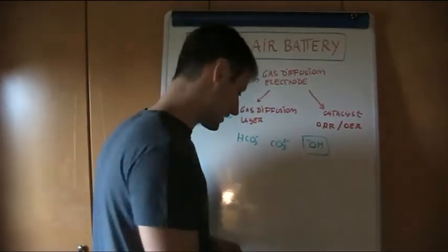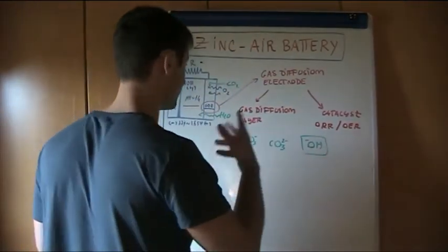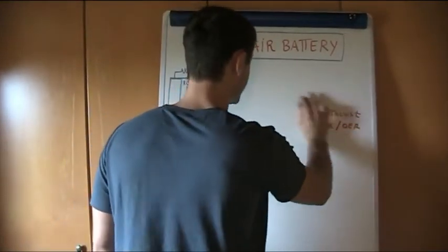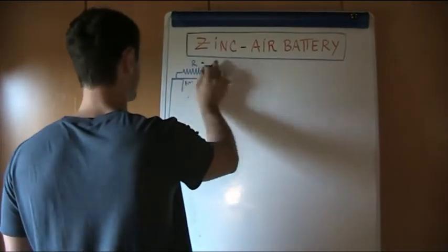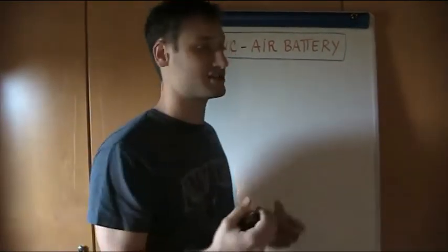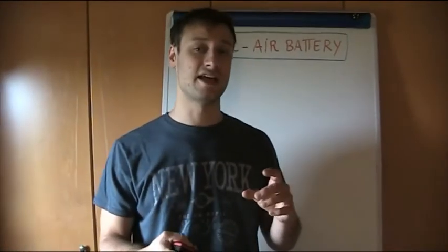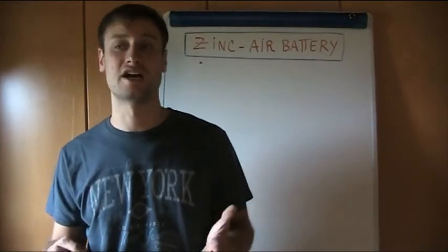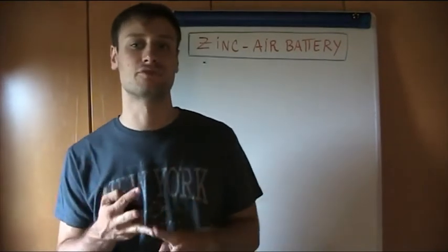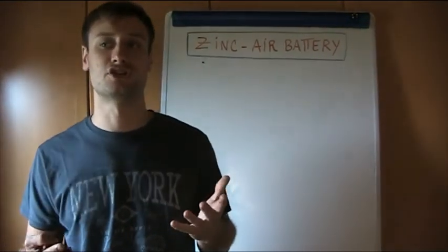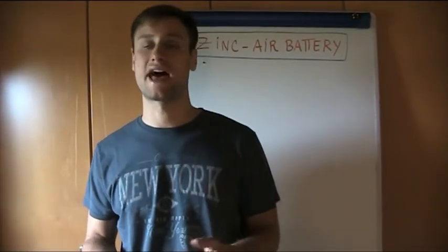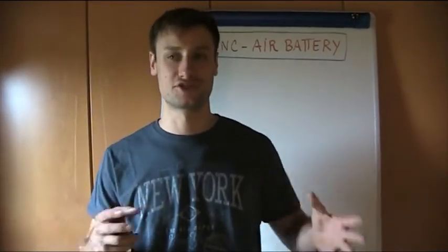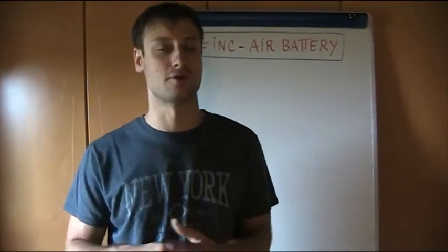Now what is important to remember is that there are different types of metal zinc-air batteries. For instance, in industry we can have a zinc-air battery using a tank of calcium oxide. Calcium oxide is used because it has a double effect. The first is to react with carbonates and carbon dioxide in order to avoid the carbonation effect, and it also reacts with the soluble product of zinc oxidation, avoiding a bad redeposition mechanism. We can even have a second tank trying to correct any changes in water and concentration in the electrolyte due to evaporation or dilution.